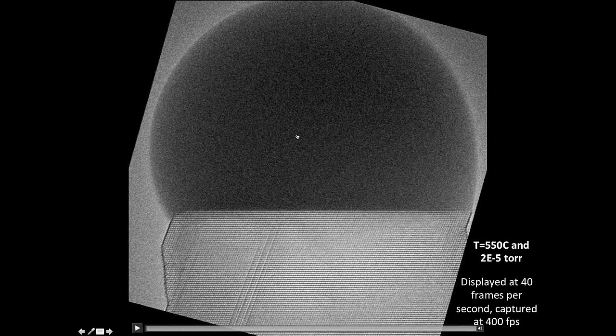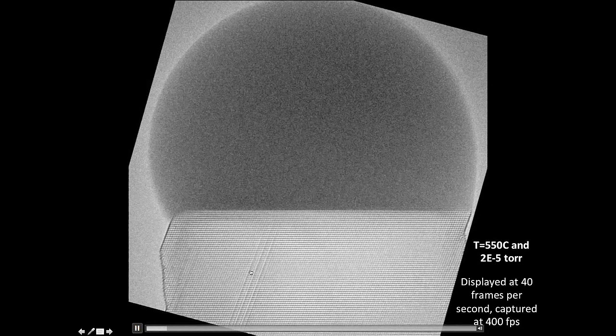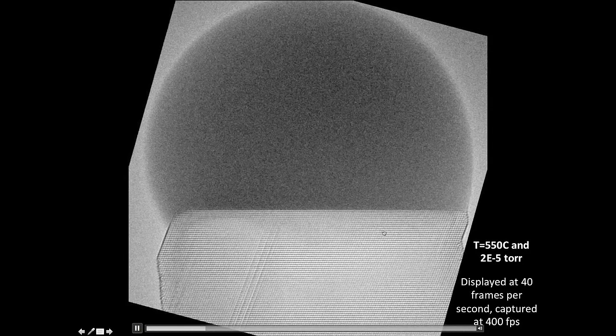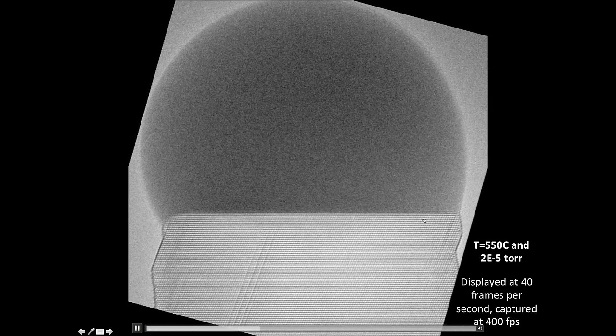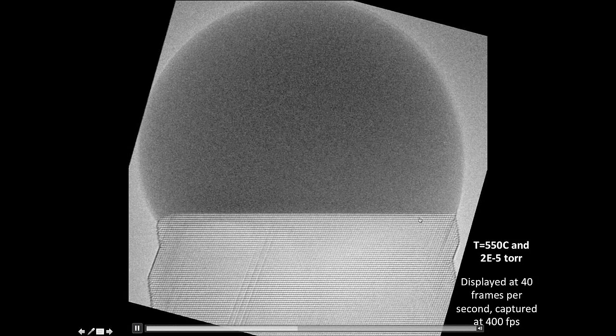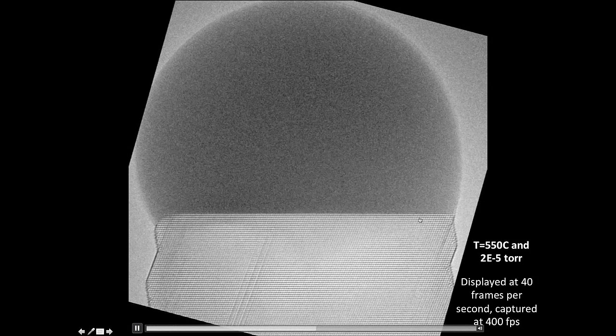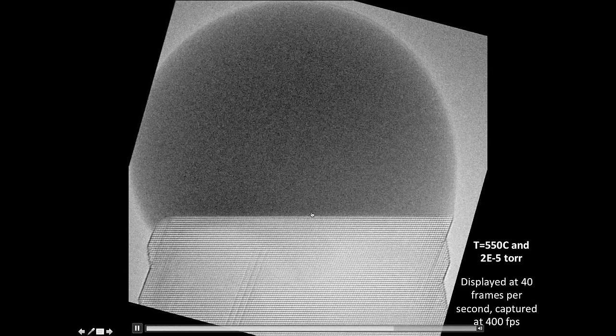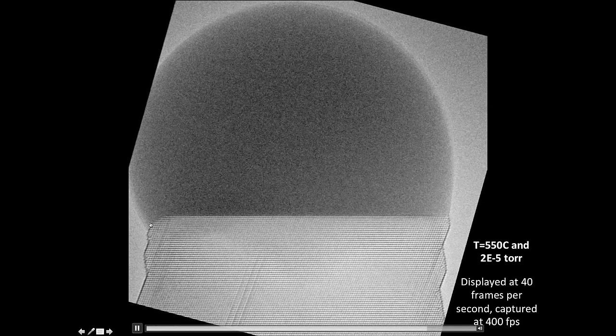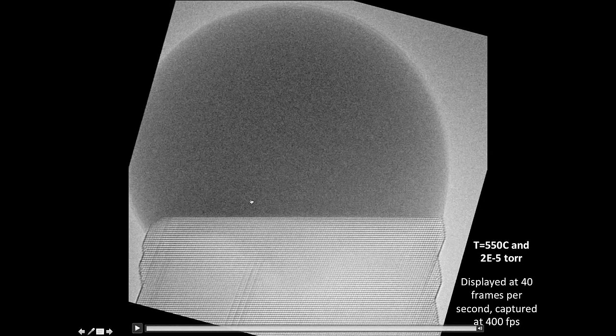Okay, so here are some images of this. Here's again a gold droplet, in this case at 550 C, at rather low pressure of disilane. I'm only going to show this at 40 frames a second. I'll show you at 400 later. It shows that you can collect at 400 frames a second and just choose to display what you need. With the aberration-corrected images that you obtain, you get very high resolution, high-quality images of this growth process. This will loop back and forth, so you can see things like the individual atomic layers as they are incorporated. You can actually check differences in how the sidewall motion occurs. I'll show you some more details of that in a second.